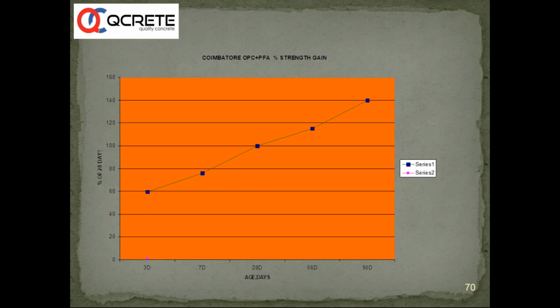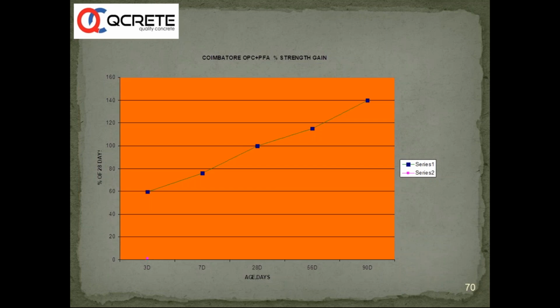So this is another slide where the slide shows significant improvement between 28 days to 90 days. We can see a jump of almost 40% between 28 days to 90 days. The fly ash was from Mettur and some fly ash came from Tuticorin. So this curve is based on more than about 600 results actually. Each result is 3 cubes actually.